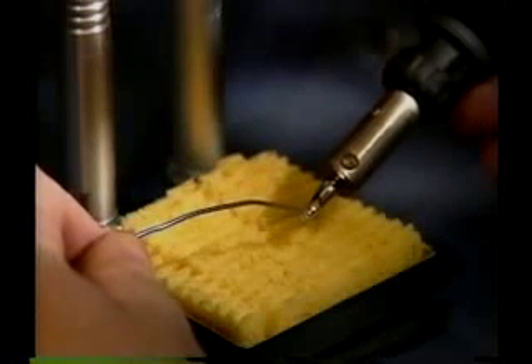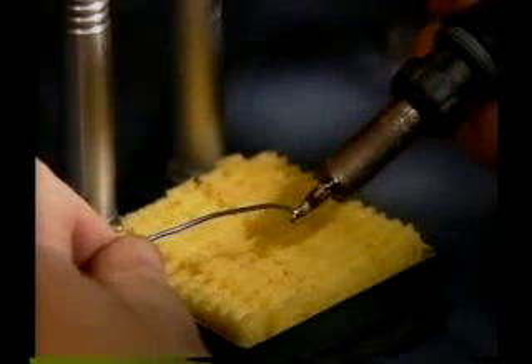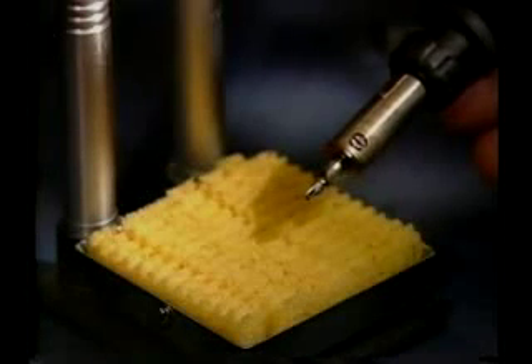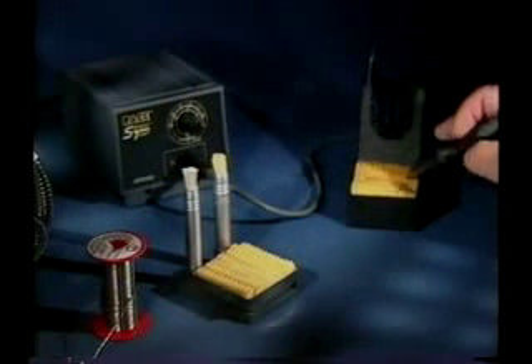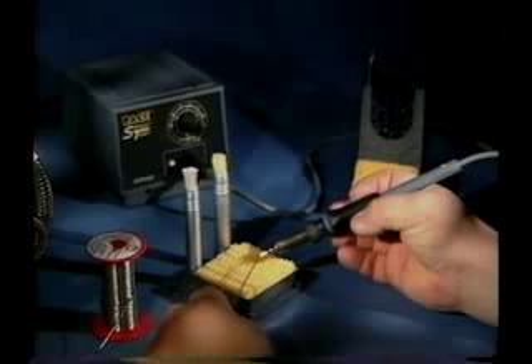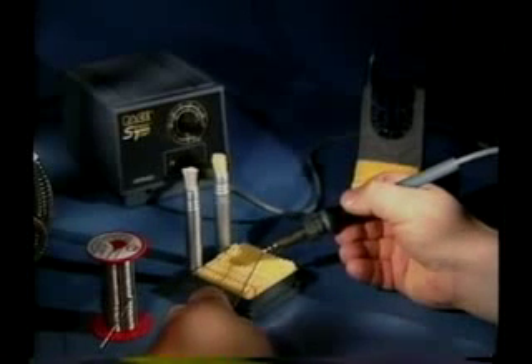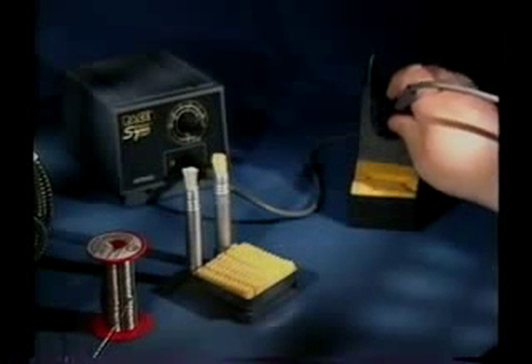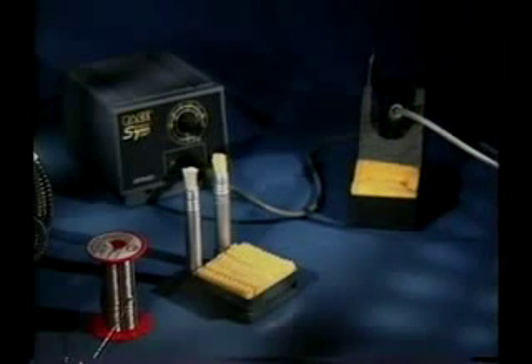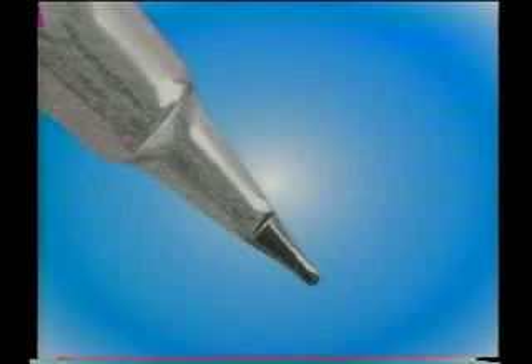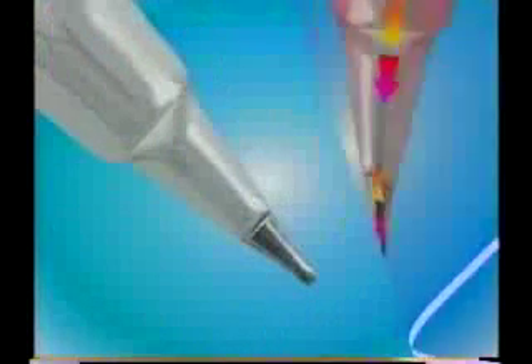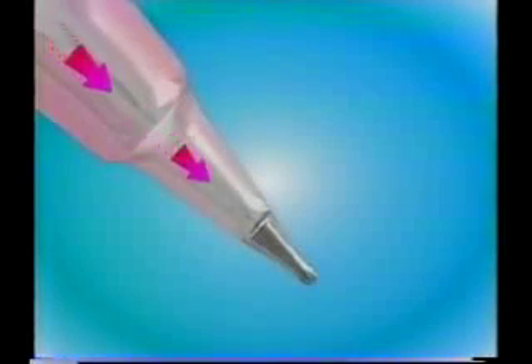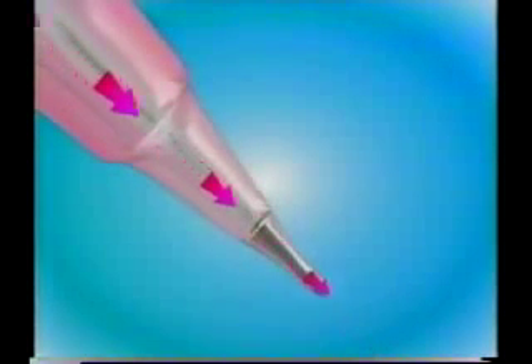The first step is to tin the tip of the iron, which will reduce the formation of oxides on the soldering iron tip itself. Tinning the tip is an important quality process control step to ensure the soldering iron tip will wet with solder and is fit for use. Oxidation acts as a barrier or an insulator, which means it slows down the transfer of heat. Tinning the tip with solder also enables the heat to transfer from the tip to the connection faster.